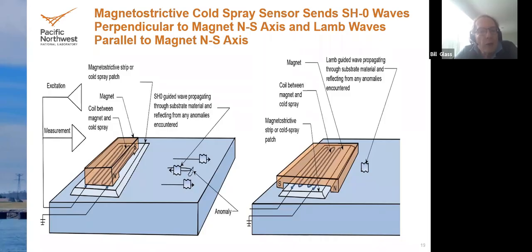One problem with magnetostrictive material, though, is that it's normally adhesively applied, and this doesn't really work well with nuclear applications. So PNNL has been exploring use of magnetostrictive material, and instead of using adhesive applied iron-cobalt strips, we've been looking at nickel and other magnetostrictive material to use and metallurgically bond these materials to the substrate, and thereby generate guided ultrasonic waves with a suitable material that can live for decades attached to a nuclear power reactor.